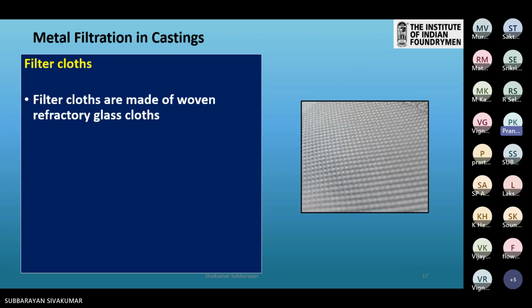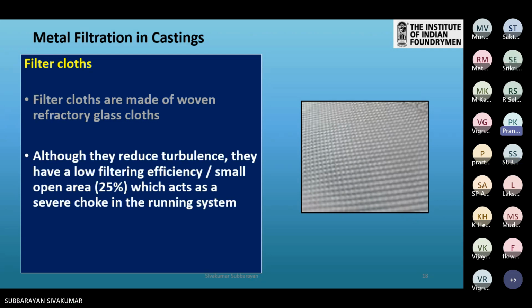Cloth filters. So these are all made of woven refractory glass. It is very thin in layer. Although they reduce turbulence, yes, obviously it will reduce the turbulence. They have very low filtering efficiency because of the small open area, which acts as a severe choke in the running system. The thickness of the filter is very low, and that metal bearing area is very less, and hence the effectiveness of this filter is very limited compared to other filters.